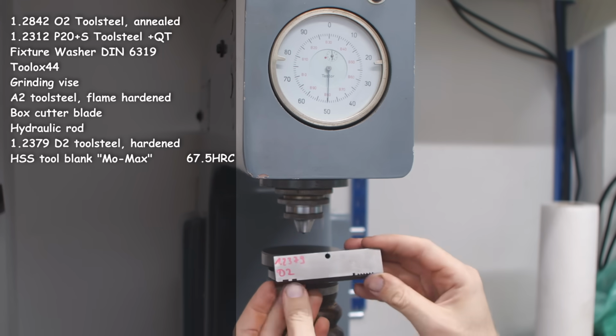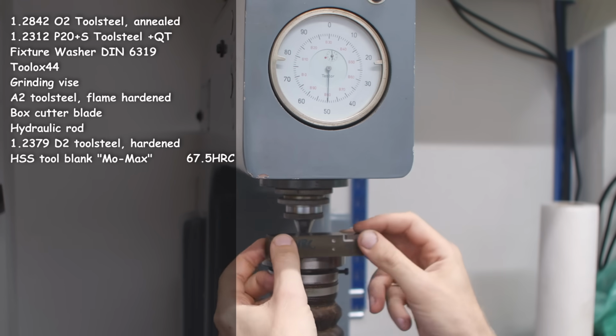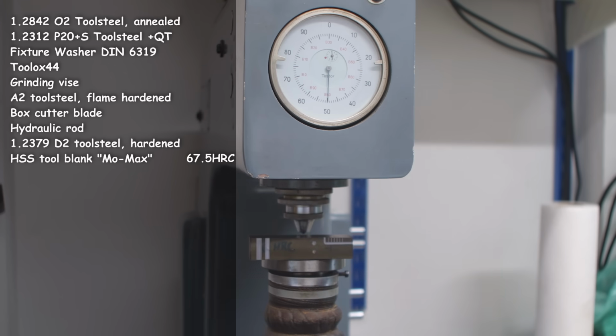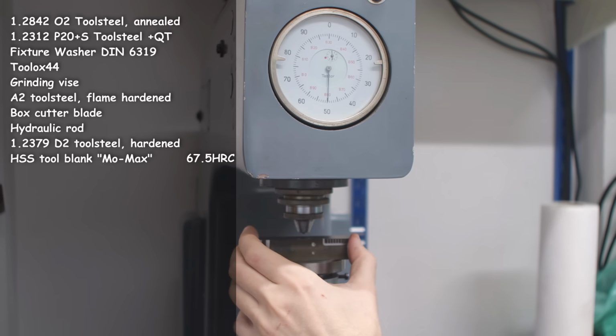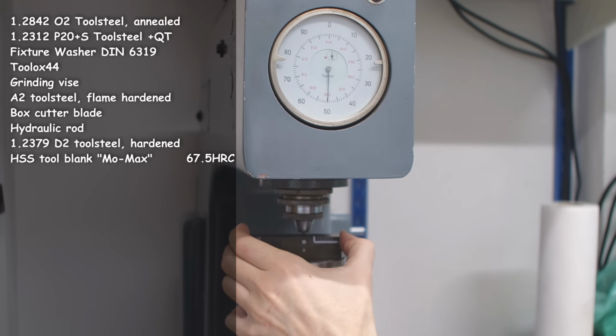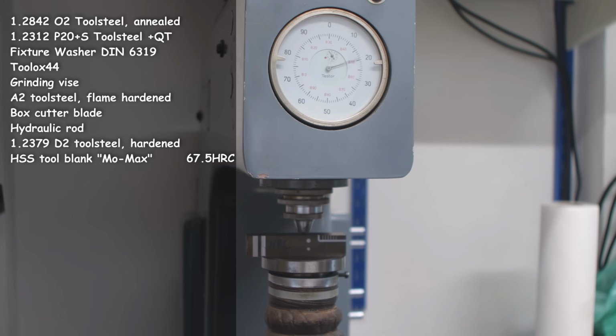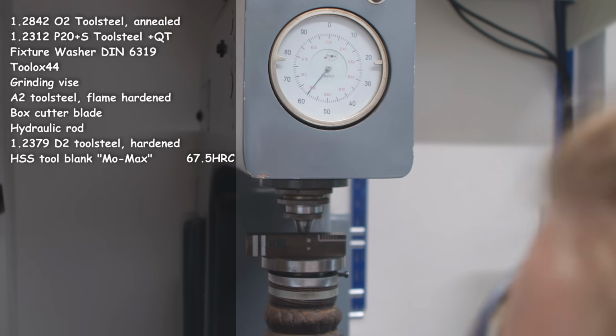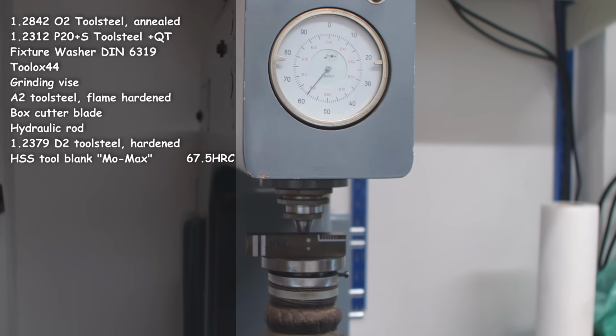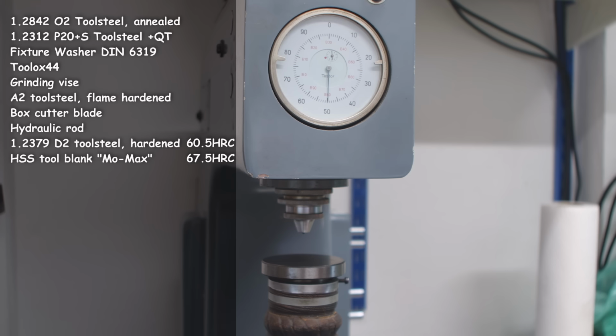The next is the D2 tool steel, also hardened. This is tool and die material. Let's drop the diamond, preload it. This is fairly hard too, and we end up in this case at 60.5 Rockwell C. So that's D2 tool steel, hardened and tempered.